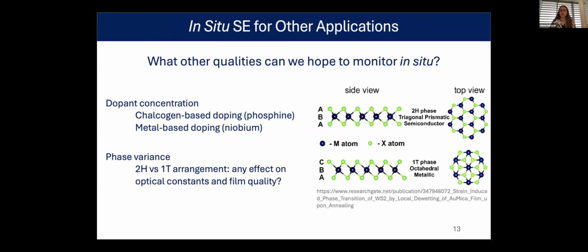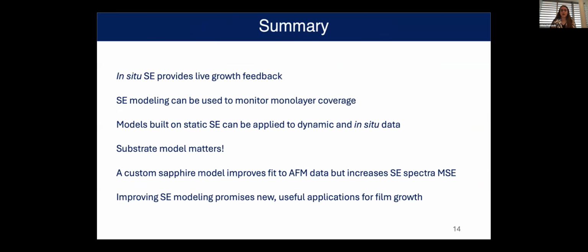And then another thing we're looking at is for this phase variance, because TMDs have the 2H and 1T phase transitions that we see sometimes during growth. And it would be very interesting if we could track that as it happens and know when, for example, the 1T phase might appear and then disappear by the end of growth. So it would be more informative.